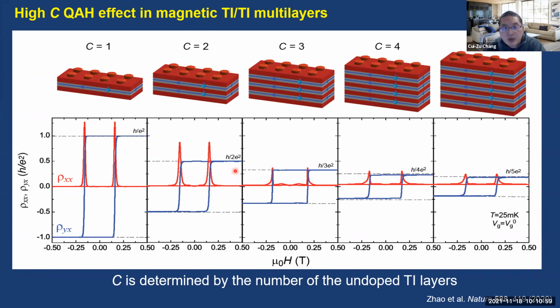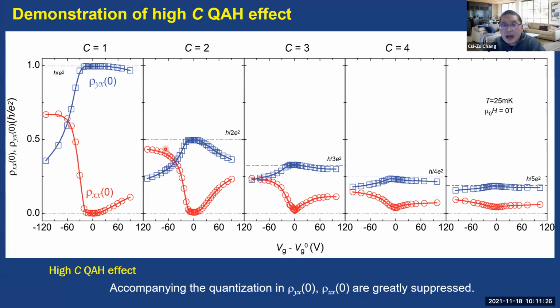This observation indicates the realization of quantum anomalous Hall insulators with Chern numbers from 1 to 5. The Chern number of the quantum anomalous Hall insulator is determined by how many undoped TI layers there are in the multilayer structure. For example, if there are 2 undoped TI layers, the Chern number will become 2. And the high Chern number quantum anomalous Hall insulators are further demonstrated by the gate dependence of the ferromagnetic Hall resistance and longitudinal resistance. We can see this is quantized at h over e squared to h over 5e squared. At the charge neutral point, the longitudinal resistance is vanishing in all these samples.